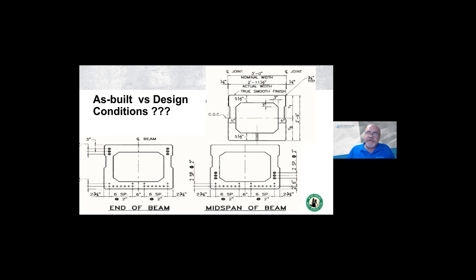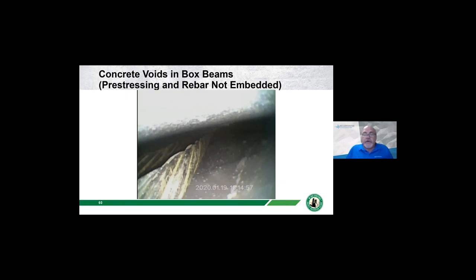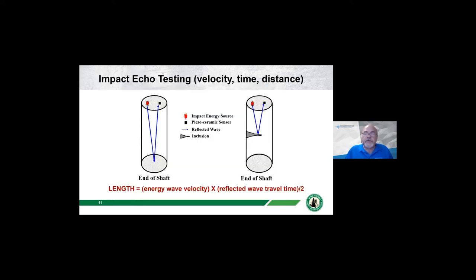We didn't always get five and a half inches in this particular case. We're looking from below, so the bottom of the beam is at the top of the image—the green line is at five and a half inches down. But the red line of what we found showed maybe two and a half inches of concrete, meaning there's a big void between the concrete poured and the bottom of the beam where the voided styrofoam block-out kicks in. The pre-stressing strands were not embedded. In fact, corrosion had already started affecting integrity, and if left untouched it would continue to deteriorate those primary pre-stressing strands.